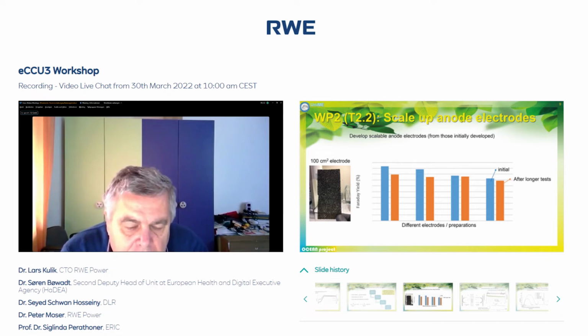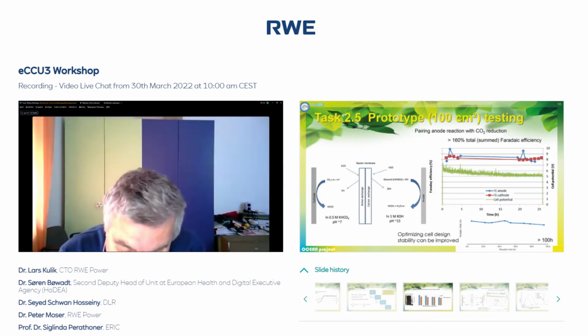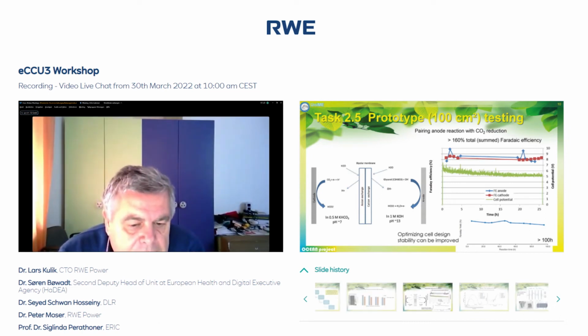Here we see the electrode. Apparently it seems non-homogeneous, but it is a really homogeneous system. We arrived at this after several tests of different materials, and again, I don't put the specific type for confidentiality, but you see that there are quite different performances, and we obtained in the end relatively stable and relatively good performance on the final electrode that we developed. The next, number 10.